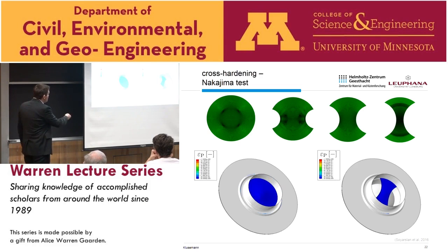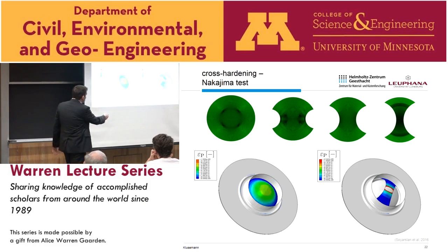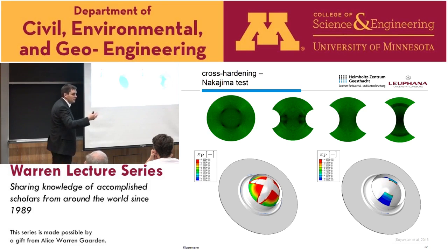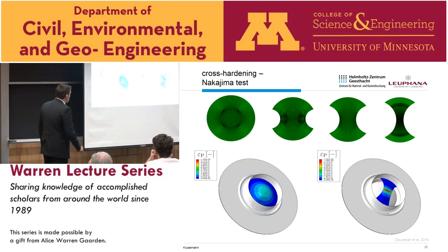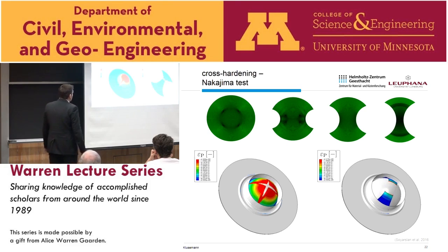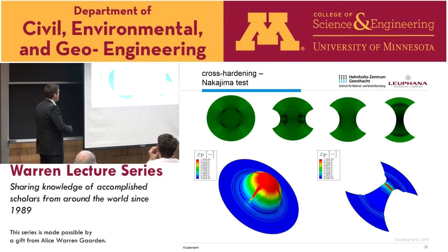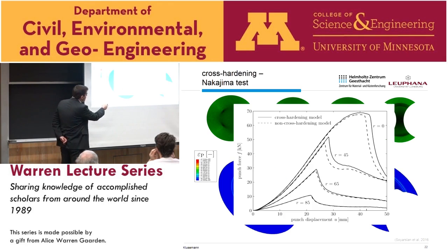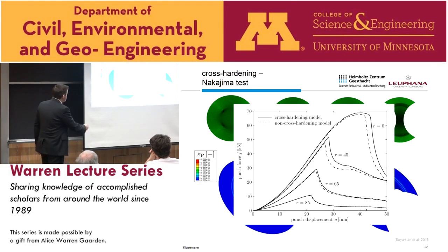So starting from uniaxial, so this is a uniaxial stress state, coming here to a kind of biaxial stress state. And what you can see here from the simulation is, first of all, in the uniaxial state you have a much earlier failure behavior, which is also classically known, compared to the biaxial. So we investigated this then, of course, also quantitatively. You see here the punch force with respect to the punch displacement, just for the simulation. For the different radii, for this one it's very low, and then if you increase, it has to be higher, there's more material, obviously.